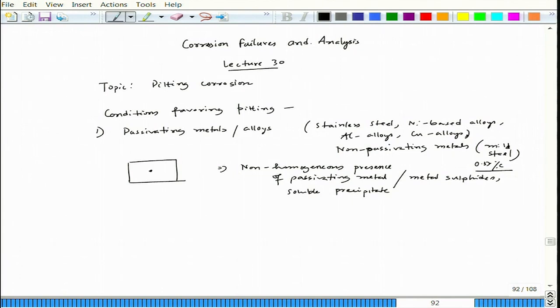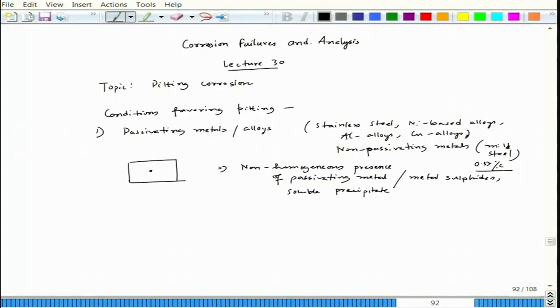If a small tiny pit forms and the rest of the surface is passivated, that small pit will act as anode and will not spread out laterally. Since the entire passivated area acts as cathode, it provides a large area for cathodic reactions. To supply electrons for those cathodic reactions, serious dissolution occurs along the depth direction in that microscopic pit zone — the pit grows very rapidly in depth. This is essentially galvanic corrosion: small anode and large cathode.